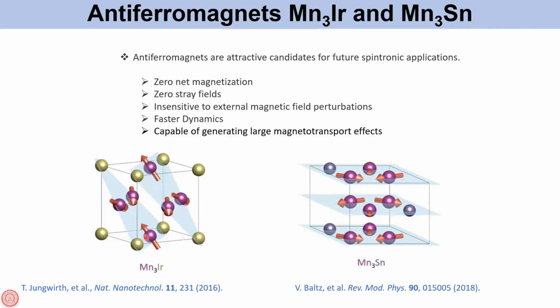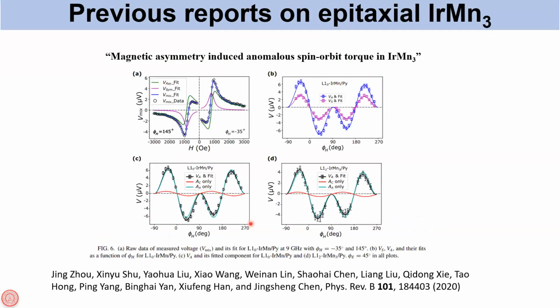So in particular, I'm going to discuss this Mn3Ir and Mn3Sn, and the crystal structure of these two metals is shown here. And there has been already a lot of work on these two materials. So here they have this structure which is non-collinear antiferromagnet. So the magnetic moments are not 180 degrees to each other, but they have a certain angle, but the net magnetic moment is still zero. And they have this so-called Kagome lattice, which I will discuss in more detail later on. And in particular, let me start with IrMn3. And there has been one work before, in fact, from Singapore only, where they have shown that you can use the magnetic asymmetry of IrMn3 to generate unconventional spin orbit torque.